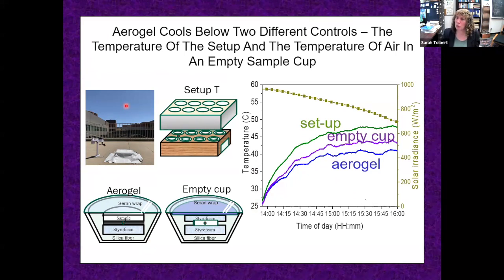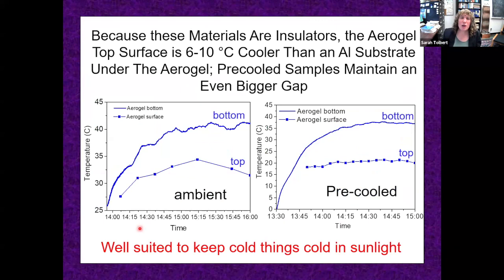Now, our material is porous, which means it's an insulator, and we actually measure the temperature at the bottom of the sample, underneath it. And so in theory, the top should be even cooler. And so if we measure the top, we indeed find it is almost 10 degrees cooler than the bottom.